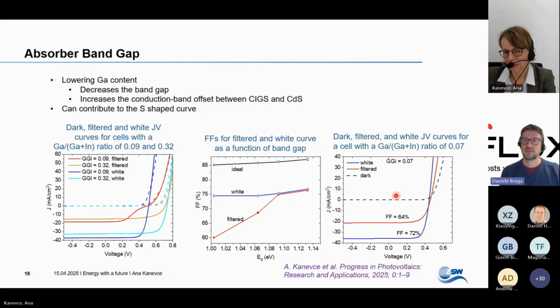Yeah, another one from Adam. Have you tried using something like ALD zinc magnesium oxide as a buffer layer to get away from the cadmium sulfide completely? It could also provide you with a means of conduction band alignment towards lower energy gap CIGS. We tried different things. We keep on trying, but still the cells with cadmium sulfide have the best VOC. We tried ALD layers with different buffer layers, with different window layers, all sputtered, chemical bath deposition. The study of alternative buffer layers is more important now. Yes, we try different things, with mixed success, I would say. Some of them are getting rid of fill factor issues beautifully, but then we get VOC losses.